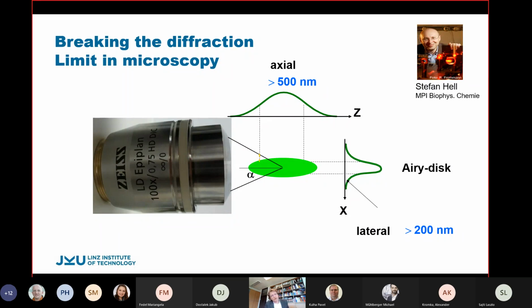And for fluorescence microscopy, as an example, you excite the fluorophores, and in the lateral direction, with the best objective lens you can get, it gives you a third of the visible wavelength, so let's say 200 nanometers. And when you confocalize it in the axial direction, it gives you the wavelength. So that's it. And if you have 2 fluorophores or 3 fluorophores in there, then all these fluorophores will fluoresce, and you cannot tell which one of those actually is fluorescing.